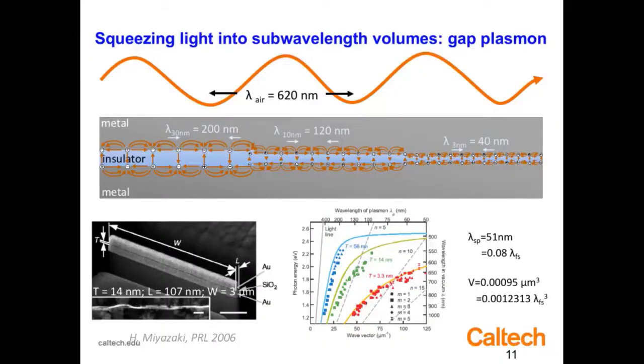If instead you saw in glass or in metal, you would say it was a different color, because the lexicon of optics has to be carefully defined: in dispersive materials, we don't have a linear relationship between frequency and wavelength. You can see here the frequency of light in free space is the same as it is as it goes into this gap, but the wavelength has shrunk dramatically from 620 nanometers in free space down to 200 nanometers inside a 30 nanometer gap, 120 nanometers inside a 10 nanometer gap, and down to 40 nanometers. Now that's more than a factor of 10, about a factor of 13 smaller wavelength. So, honey, I shrunk the wavelength inside this gap of the materials.